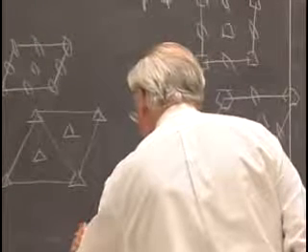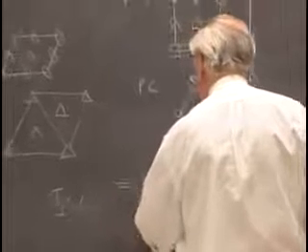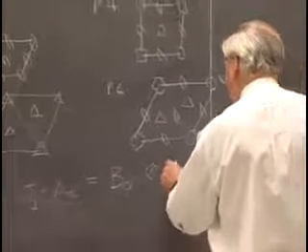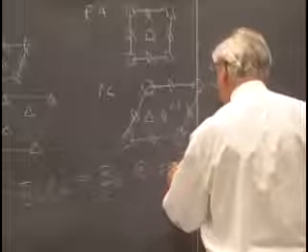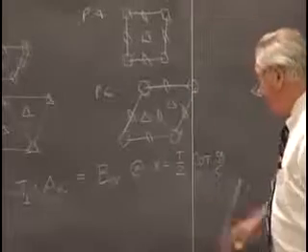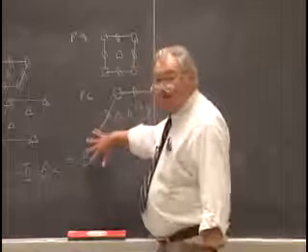lattice point. Deriving these, we used one theorem, which it's well to remind you of, and that is that if I have a rotation operation, A alpha, follow that by a translation that's perpendicular to the rotation axis, what I get is a new rotation operation, B alpha, and it's located in a very specific location, and that is at a location that's a distance x equal half the magnitude of the translation times the cotangent of alpha over 2. So this combination theorem, if nothing else, reminds us that these combination theorems, as I call them, are not equations in symmetry elements. They are equations in individual operations.